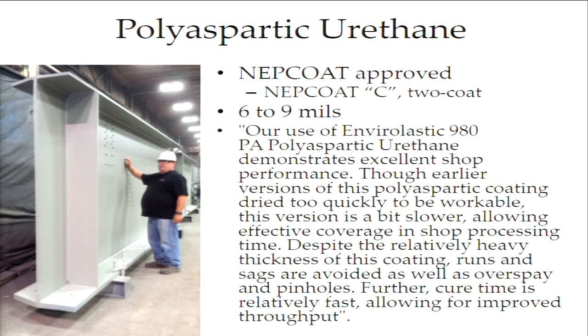And they dialed it back a little bit. And so we said, well, sounds good, but you know, is it really going to work? We did some tests, and we really liked it. This is Pat, who runs our paint bay, and these were his comments. You can read them. We've since done 2 jobs with the polyaspartic. You know, if you think about the 3-coat versus the 2, as Jeff mentioned, you add the epoxy, it gives you a barrier, but it helps you bind the urethane. The polyaspartic accomplishes what both of those coatings do.